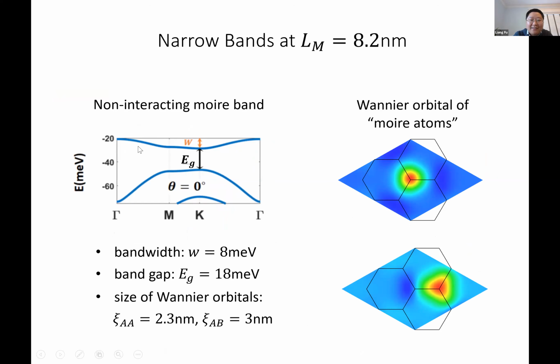So in this case, we see that as the Moiré period increases, the band becomes much flatter. The bandwidth is reduced to only about 8 milli-electron volt. The first and second bands are separated by a gap of about 18 milli-electron volt. And when we look at, for example, the first two bands, the Wannier functions are very well localized in the primary and secondary minimum, in the AA region and in the AB region. The size of the Wannier orbitals is about 2 or 3 nanometers, considerably smaller than the period.